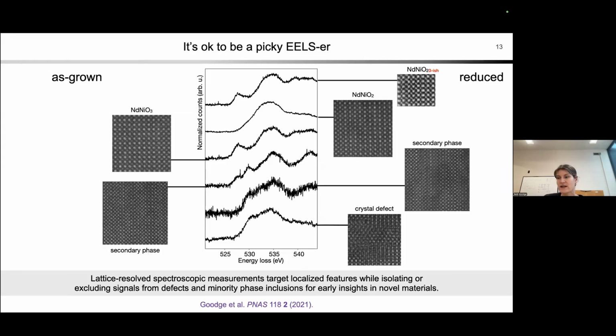And so in particular, if you want to learn about the electronic structure, if you want to do some kind of spectroscopy, for instance, you need to know about all of these different phases that exist in the material, because you can see from these isolated sections that I have here by EELS, they're each contributing their own spectroscopic signature, right? And so there's all these different spectra that are coming out. And you can imagine that if you're just doing a bulk spectroscopy, from X-rays or whatever, and you can sample only everything on average, that's going to give you not exactly just the signal from the region that you're interested in. So one of the key advantages that we have with a very local measurement like STEM is that we can actually go in, we can find the regions which are the thing that we're interested in studying, and we can just do very local measurements to target, in this case, the spectra or the spectroscopy of just those kind of locally pristine regions.